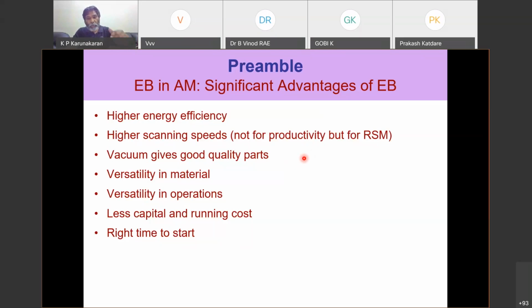But when you scan at 10 meters per second, the material also has to respond. It should be able to absorb that kind of heat. So in plastic, you are probably able to go up to 4 meters per second or so, but metal doesn't absorb that fast because you need to transfer a lot of energy to melt it. Okay, the latent heat is high. Therefore, typically in metal additive manufacturing using the SLS process and all, they limit to 2 meters per second. Otherwise, the motion system is capable of going at 10 meters per second.